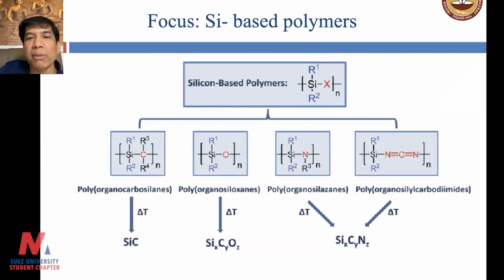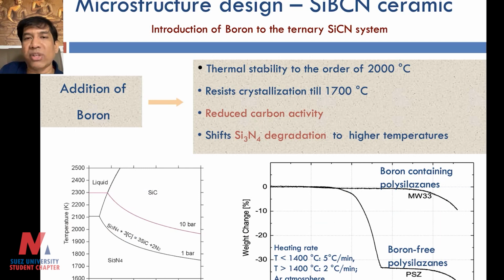Just to give you the chemistry part, I don't know how many of you understand the materials chemistry part, but we have been working on silicon-based precursors, and depending on what goes into the backbone here, you can actually make different kinds of materials. For example, if silicon and carbon are in the backbone, you are actually making silicon carbide to begin with. And if silicon and nitrogen are in the backbone, then you make silicon nitride. If oxygen is in the backbone, then you make silicon oxycarbide. So it gives you a lot of flexibility, if you're a very good materials chemist, in making different materials.